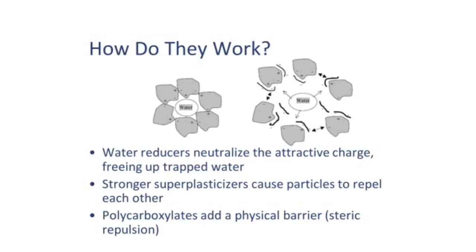The chemistry behind polycarboxylates is even more complex and more sophisticated, because instead of just acting like a dryer sheet that you throw in your dryer so your socks don't stick together, these actually have polymers that coat the particles and act like a physical barrier that helps separate the particles. It's called steric repulsion. It's pretty cool technology, and that's why SCC — or self-consolidating concrete — uses these polycarboxylates. You can use a lot less water and still get a lot of lubrication, so your particles just slide around each other. Very, very potent, very powerful, very versatile.